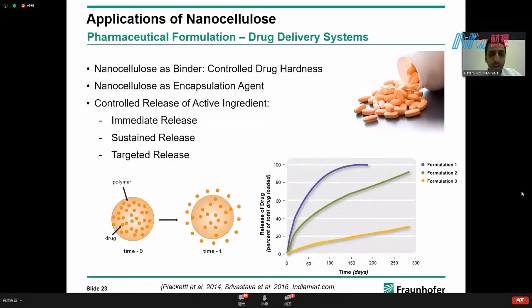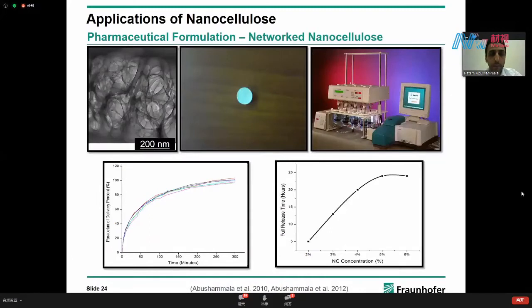And this was actually part of work I did about 10 years ago, where I made this special kind of nanocellulose. It's network nanocellulose, as you can see here in the photo. And I was able to encapsulate paracetamol inside. Depending on the amount of nanocellulose, I was able to control the release time. With small amounts of nanocellulose, we are talking about 2% to 6%, I was able to control the release from 5 hours to 25 hours. And this makes such a material a universal excipient for many different active ingredients.